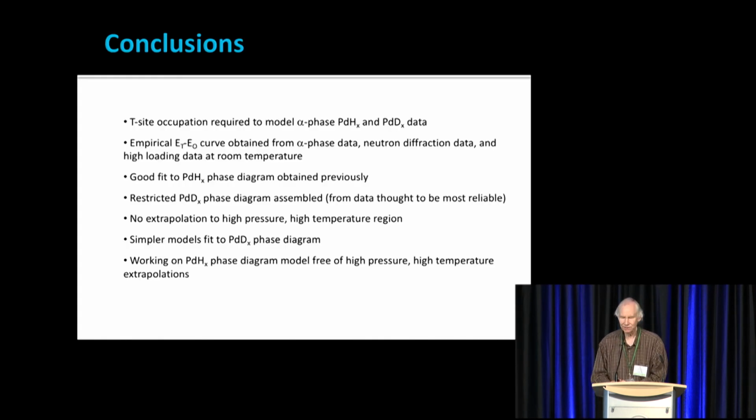Anyway, the conclusion is I think these models are interesting. I think T site occupation, especially at low loading, is predicted. It's consistent with the best DFT calculations. There's weak experimental data, but some experimental data from neutron diffraction to support it. Much more can be done to remove uncertainty, and should be done. Anyway, I'll stop here. Thank you.